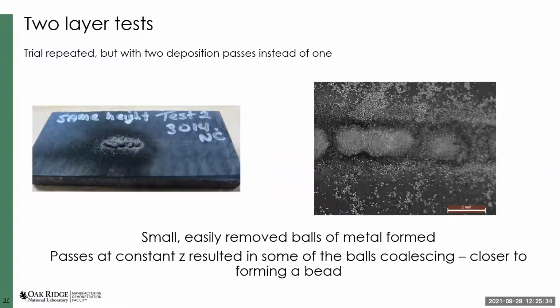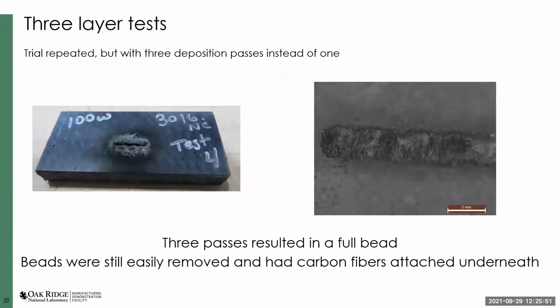So we just started doing multiple passes. When we tried 2 passes, we did get more coalescence of the metal into metal balls and almost a resemblance of a bead, but definitely not a full bead. And then once we hit 3 layers, we actually did get a fully deposited bead. It is easily removed, which is very exciting because the goal of this research is to investigate support structures. So the fact that the polymer comes easily off of the metal is very exciting. On the flip side, you can see that there are actually carbon fibers embedded in the bottom of the metal bead, which is a little less exciting.